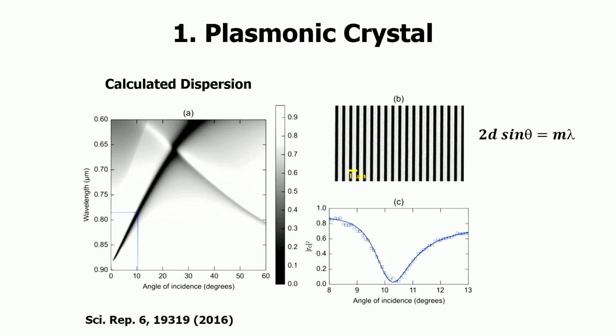As the incident angle changes, the plasmon resonance which is excited changes. So there's a dispersion. In addition, the line width is varying as we move along the y-axis. So as you change the incident angle, the resonance is also changing and the line width is also changing. Basically, the plasmon dispersion shows that the lifetimes could be different in these structures.